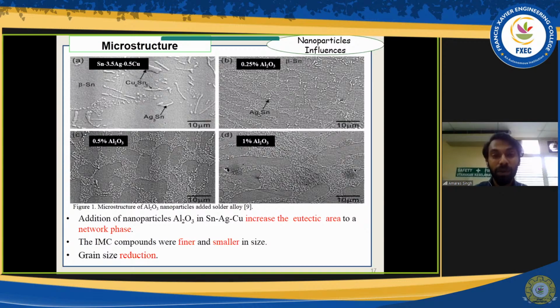What happens is that when the grain tries to grow, these nanoparticles will impede the growing of the grain. So basically, before the grains can grow, solidification already happened. So the solders will be solidified even before growing. So there will be many tiny grains that will enhance the hardness properties. So addition of nanoparticles here is important as well, not in terms of a high weightage of amount, but a less weightage of amount, as mentioned for the wettability.